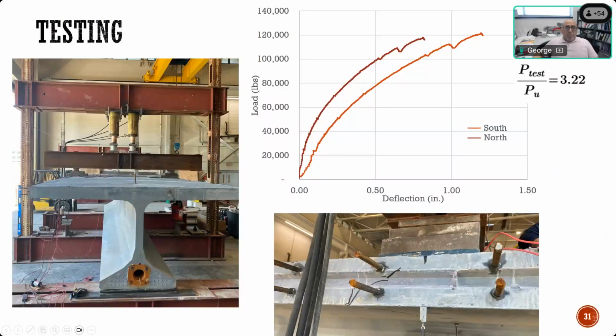We did similar testing for that as well, and it performed even better than the previous one. It performed very well. The ratio of punching load capacity to the demand at ultimate is more than 3.2, and it had very little cracking on the side and the bottom of the flange. So these were very successful specimens in terms of production.